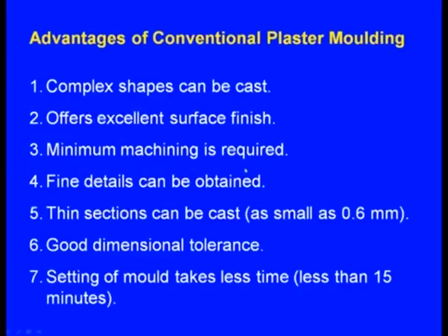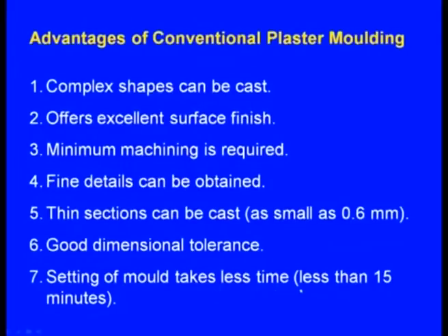Next one, minimum machining is required. Fine details can be obtained. Next one, thin sections can be cast as small as 0.6 millimeters, and this process offers good dimensional tolerance. Setting of mold takes less time, less than 15 minutes.